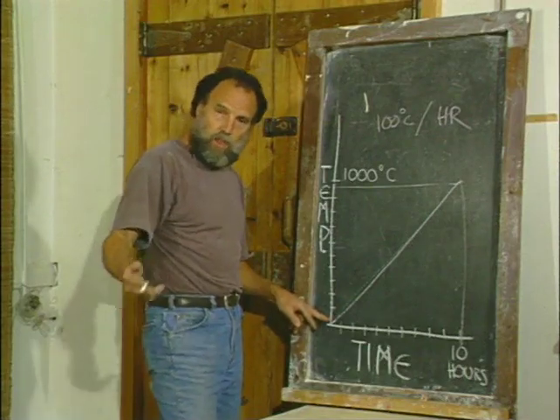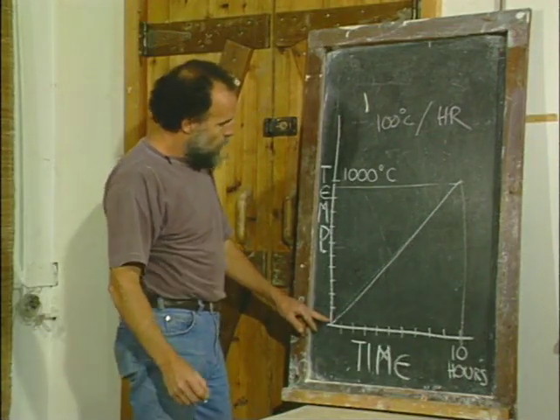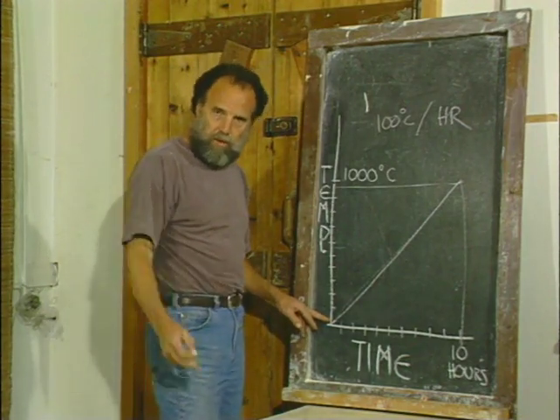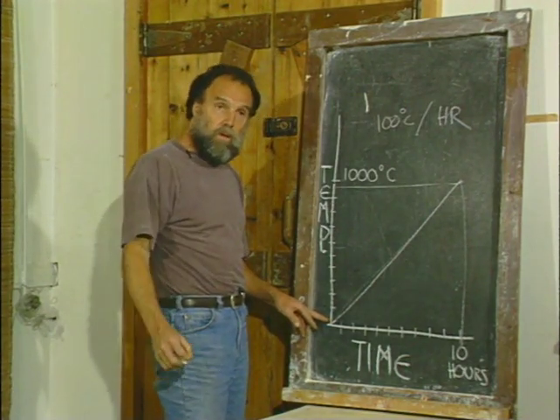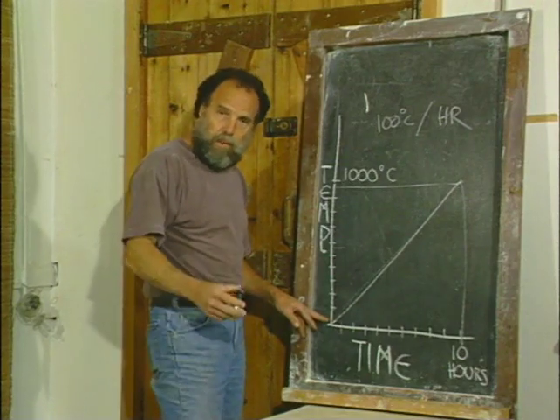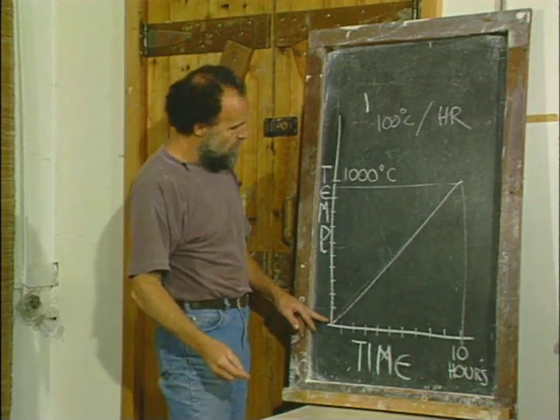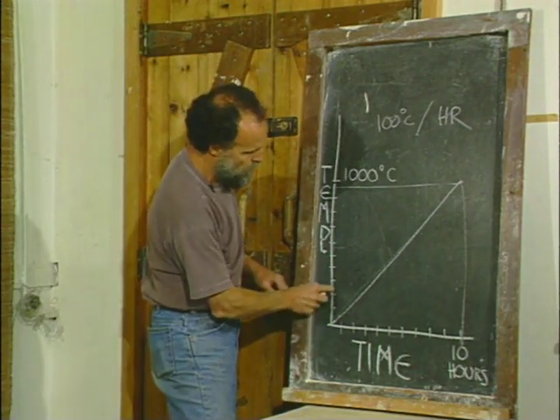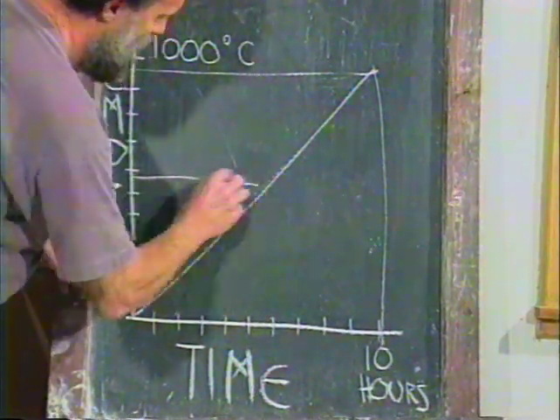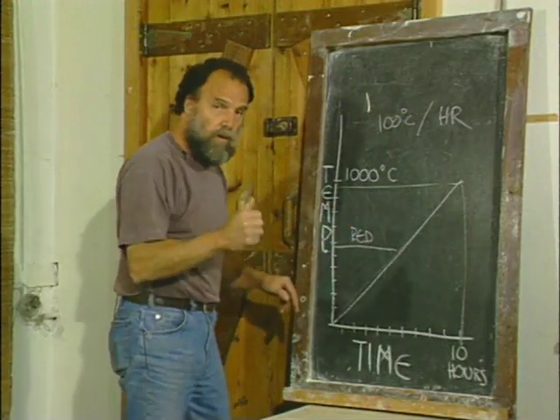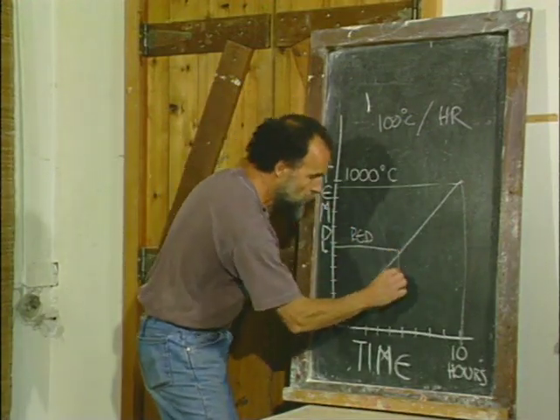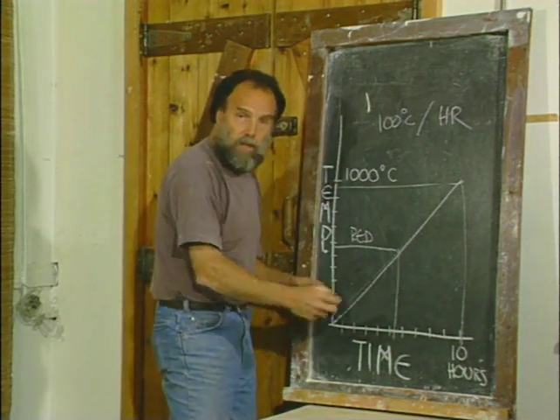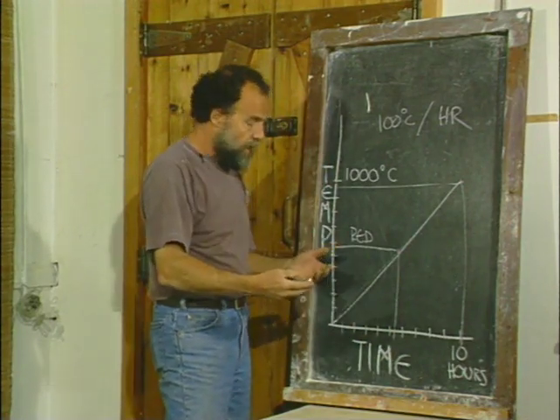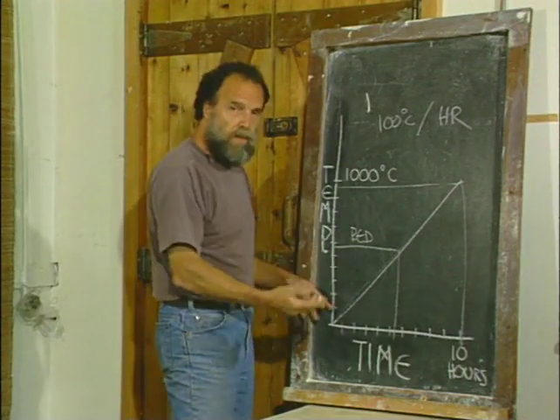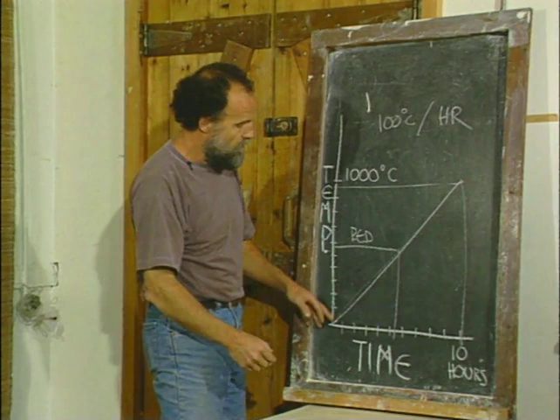Now, if you're relying strictly on visual information, really you won't be able to tell where you're at in temperature until you can see something into the kiln in through the peephole. And that will be at what's called the lowest visible red, and that's at about 550 Celsius. So that's the first time you'll be able to get an accurate realization of what the temperature is, and that should take about 5 hours. If you've got to it faster than that, then you're going a little too quickly. If it takes longer than that, then perhaps you could speed the rate of progress of the firing up.